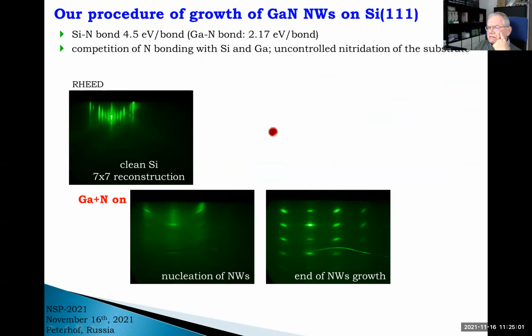Usually, the most common substrate is silicon, and what people usually do is take a silicon 111 and deoxidize it. In the RHEED pattern, you see the 7x7 surface reconstruction, which is believed to be a fingerprint of a really clean silicon surface. Whether or not this is the case, I will discuss later on. Having this surface, people usually open gallium and nitrogen sources at the same time. So there's nucleation of nanowires, and finally this kind of pattern is visible on the screen, which corresponds to nicely ordered nanowires on the surface.